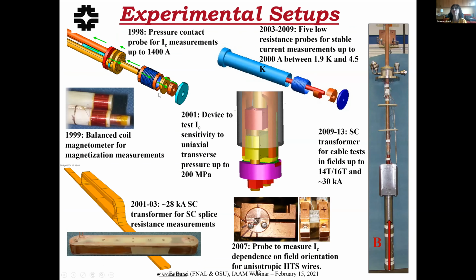So just to give you an idea, the first setups that we designed were probes to measure the critical current. We started using the ITER barrel, which had been developed within the fusion community. I started with that one because it was already developed. And here the current flows through the sample just through pressure contact with indium. But this limits the amount of current. So the more industry made progress on these materials and the better they became in current, we had to change to copper-to-copper contact to transfer the current. We developed too much resistance, so we had to go to soldered contacts. And these are long and thin because you have to plug them into this cryostat within the bore of this test solenoid at the bottom.